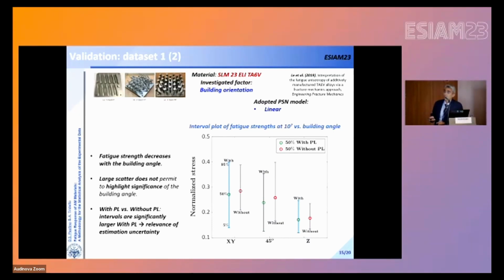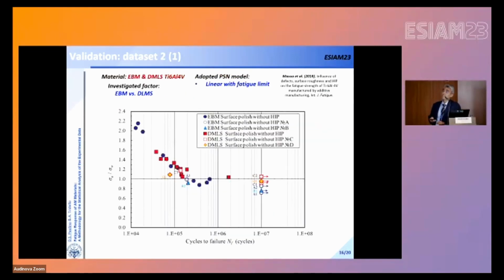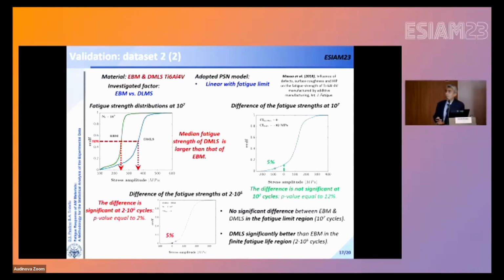So here you can see with or without. With means with profile likelihood, with uncertainty estimation, and without means without profile likelihood, by not taking into account the estimation uncertainty. A second data set is taken from Masuo et al., published in 2018. In this case, it's quite evident the SN trend is linear with fatigue limit. The investigated factor in this case is the manufacturing technology, EBM versus DMLS. By applying the methodology, we studied the fatigue strength distribution at 10 to the 7 cycles.